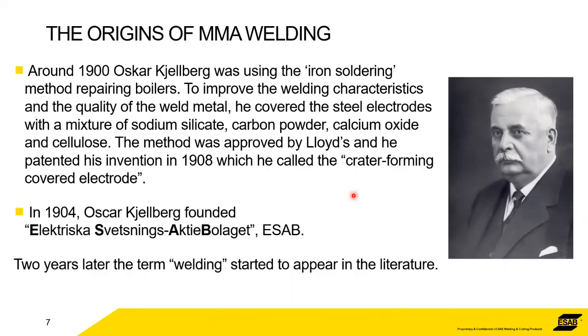So from the 1890s with Slavyanov, around 1900, Oskar Kjellberg was using this iron soldering method to repair boilers over in Sweden. And for whatever reason, he realized that he could improve the welding characteristics and the quality of the weld, keeping out porosity, keeping out the oxygen. He covered the steel electrodes in a mixture of sodium silicate, carbon powder, calcium oxide and cellulose. After lots and lots of experimentation, this method was approved by Lloyd's, and he patented his invention in 1908, and he called it at the time a crater forming covered electrode.